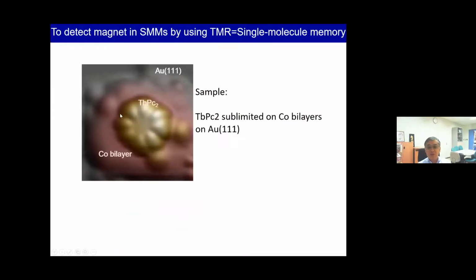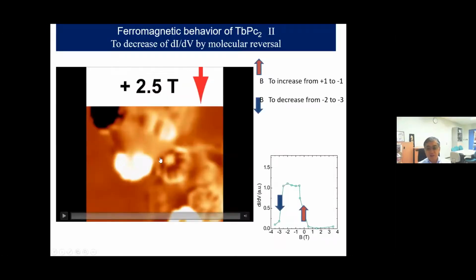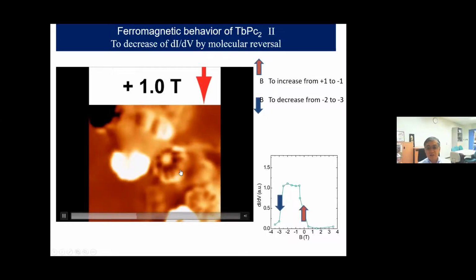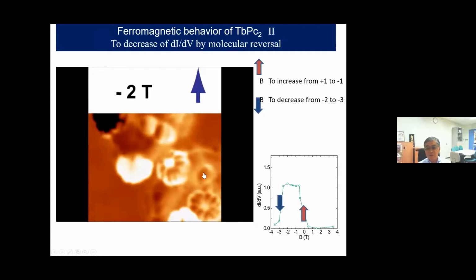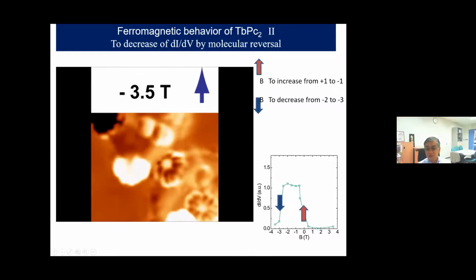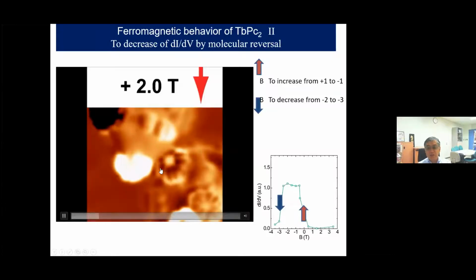So we must realize single molecule magnet memory devices on the gold surface with the ferromagnet cobalt and the single molecule magnet. This is one single molecule magnet. The external field is around 2.5 here. Now the spin is down, dark color. Okay, we decrease the external magnetic field. Now the color is bright. Now the spin changes. We see from spin down, decreasing the magnetic field, spin up, spin down. We put the information, one spin, into the one single molecule magnet, up spin or down spin. Now darker, spin up.